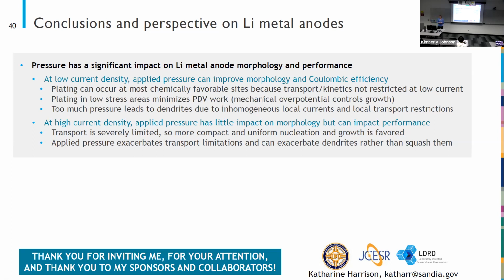Too much pressure, it has to be a lot more pressure, something like 10 megapascals, will actually lead to dendritic growth because of the inhomogeneities in local currents and local transport restrictions. At high current density, the story is different, and applied pressure has less impact on morphology, but it can still impact performance. Transport is very limited and kinetics are limited in general, so we get more compact and uniform nucleation and growth, and that's favored because we just have to plate everywhere if we're trying to keep up with that high current. The applied pressure exacerbates transport limitations, and so it actually exacerbates dendrites rather than squashing them.